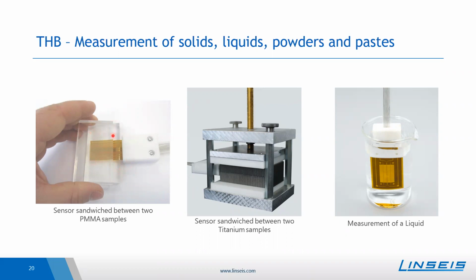To enhance the thermal contact between the sensor and the 2 sample parts, one typically presses the configuration together. One can use, for example, such a manual press for it. So that also, for example, compressible materials like foams can easily be measured without pressing the material too much together.